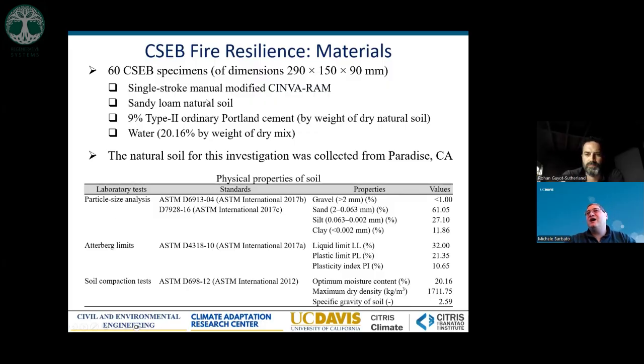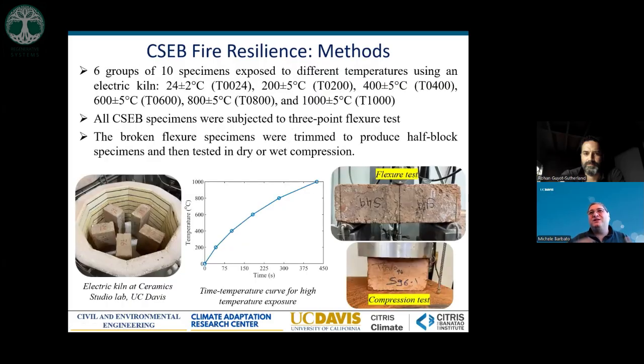We were still using our manual CINVA-RAM, the blue machine that I showed you at the beginning, which requires a lot of work. So we did only 60 specimens for this investigation. These specimens were divided into 6 groups of 10 specimens. Some were left at room temperature, and then others were tested under 200 Celsius, 400 Celsius, 600 Celsius, 800 Celsius, and the 1000 Celsius that I indicated before, the 1800 Fahrenheit, which is a very high value of temperature for a wildfire.